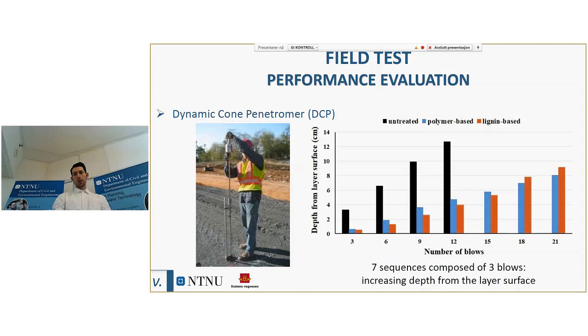Of course, we also have different or simpler methods to assess the validity and effectiveness of such additives. The first one, for example, was to use the dynamic cone penetrometer, the DCP, and the way of using this device is simple. We just have a vertical rod. The conic end is placed on the top of our layer, and then there is a falling mass just falling down and hitting the cone, so that the cone end can penetrate down in our base layer.